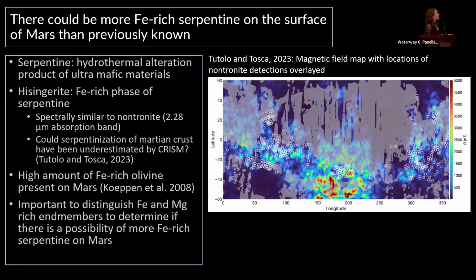So to get started, serpentine is a hydrothermal alteration product of ultramafic materials, and it has been detected previously on Mars using CRISM data. However, it has been hypothesized that the amount of serpentine has been underestimated on the Martian surface. And this is because of the similarity between the spectral signature of nontronite, an iron-rich smectite, and hisingerite, the iron-rich serpentine. They both have a band at 2.28. So where we have detected nontronite, some of it may have actually been hisingerite. And it makes sense we may see some iron-rich serpentine on the surface of Mars because of the iron-rich olivine that is abundant on Mars. So this motivates my work because it's very important to distinguish iron and magnesium-rich serpentine so that we can see if we are actually missing the signatures of iron serpentine.